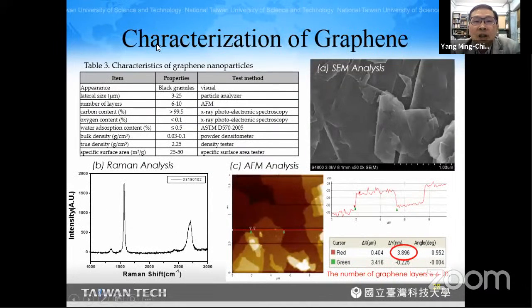And this figure shows the characterization of graphene in our experiment, and here are the characteristics of the graphene nanoparticles. This figure is the result from SEM analysis of these graphene flakes, and we also use Raman to analyze the structure of graphene. We can observe the characteristic peaks of graphene in this spectrum. And we also use AFM analysis for the thickness of these flakes.